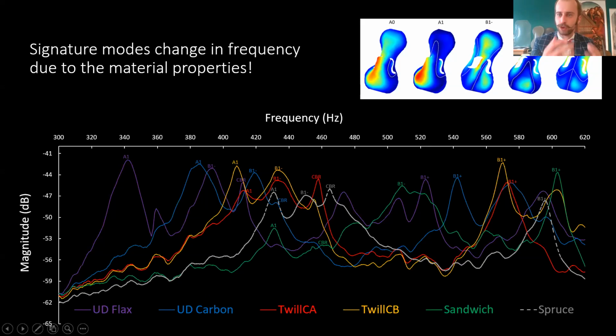So the fact that it's unidirectional makes, again, the frequencies lower, but because it has less weight, it's a little bit higher than the flax violin. So these are two unidirectional ones, heavier one and more lightweight. Then you see the TwillCA and the TwillCB. These had a little bit higher stiffness in the transverse direction. So in this direction, it's a little bit stiffer.